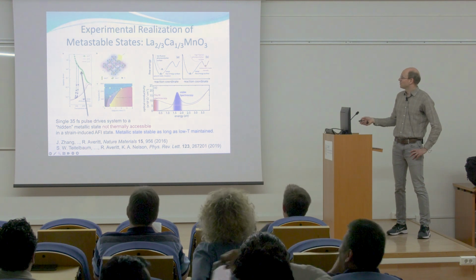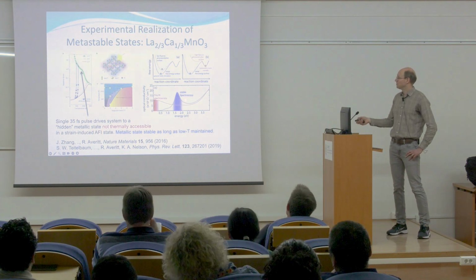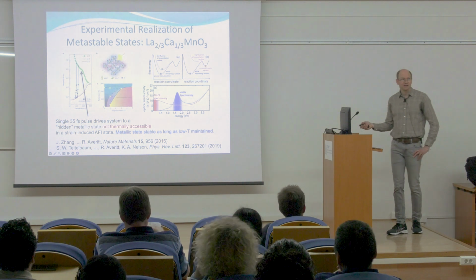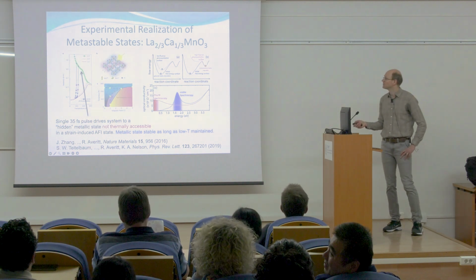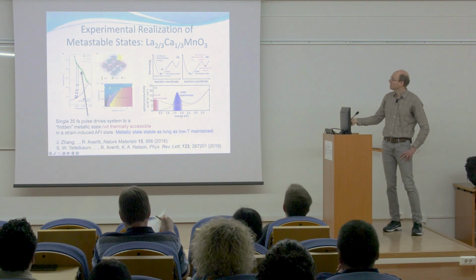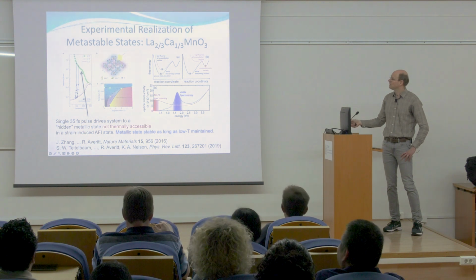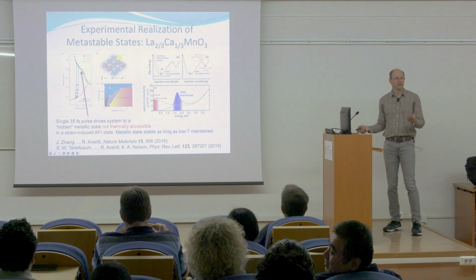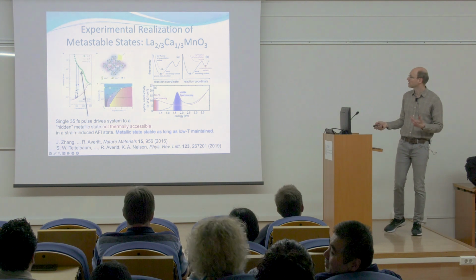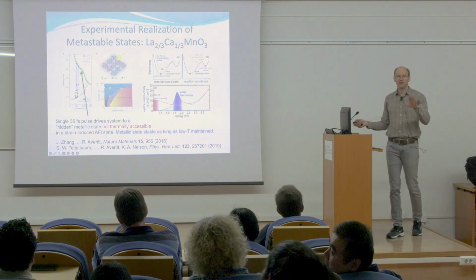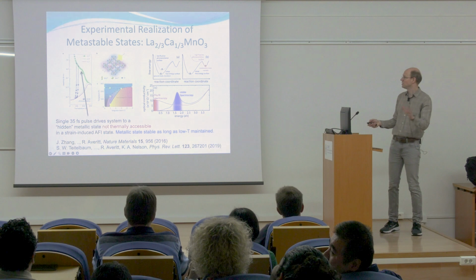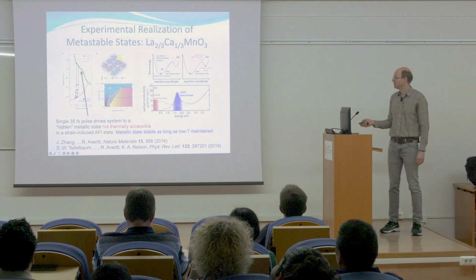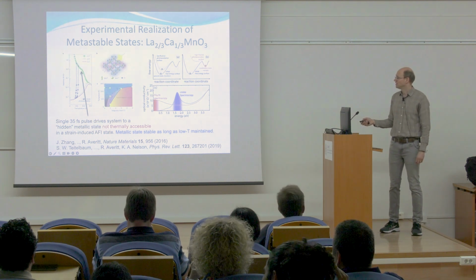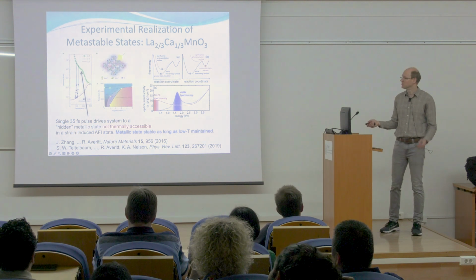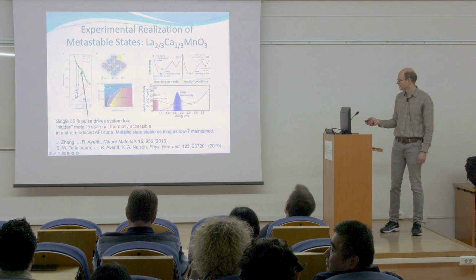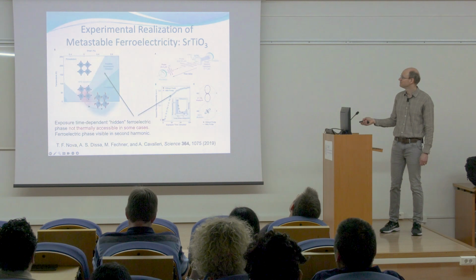If you look at other properties, such as how the system absorbs or reflects light, then you see the same sort of properties there. So this is a measurement which can be done on a much faster time scale. So resistive measurements cannot be done so quickly. However, light reflectance or transmission experiments can be done very rapidly. And so they're one of the tools in order to observe very rapid changes in behavior in a system.